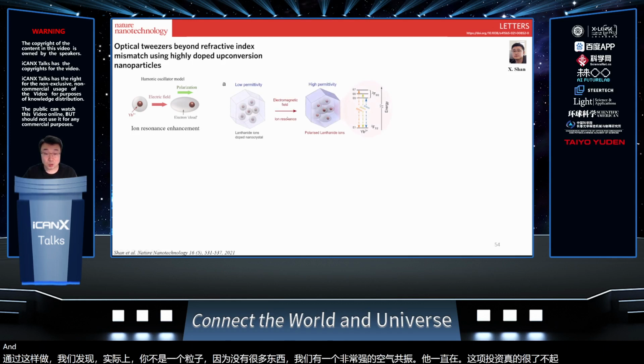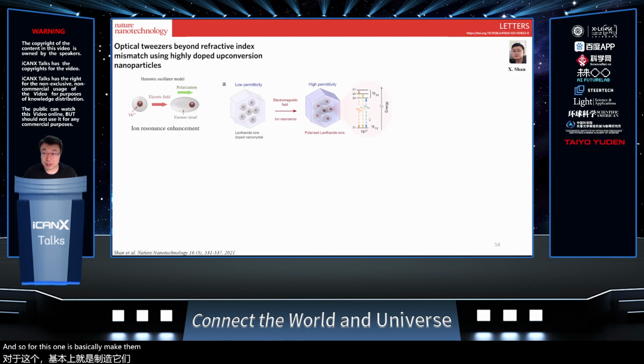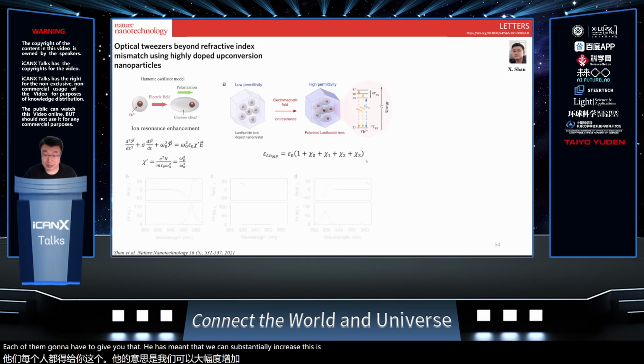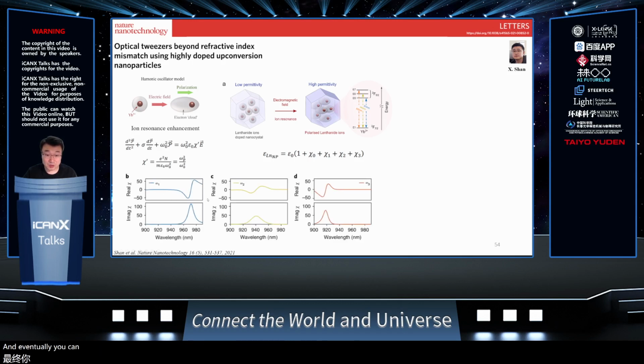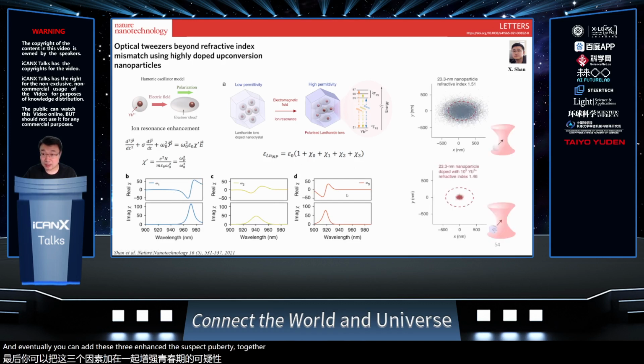For this, it basically makes the ytterbium ion have the resonance, so it has three levels. If you look at these three levels, each of them gives you enhancement that can substantially increase the susceptibility. Eventually you can add these three enhancements together, and finally you can enhance the trap stiffness. This red circle is our laser beam. For a really low refractive index nanoparticle, like refractive index 1.5, you couldn't trap it, because the position sometimes jumps off from the trap.